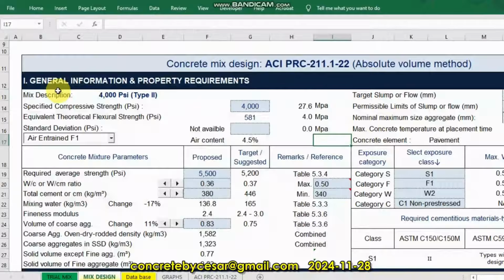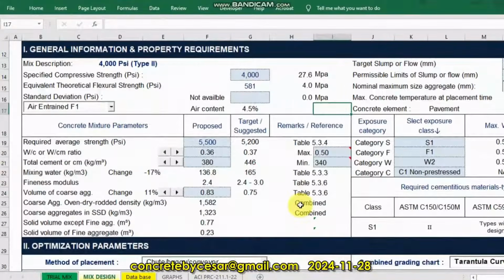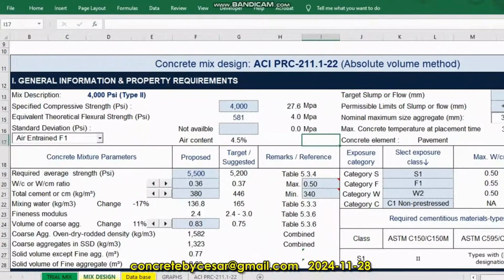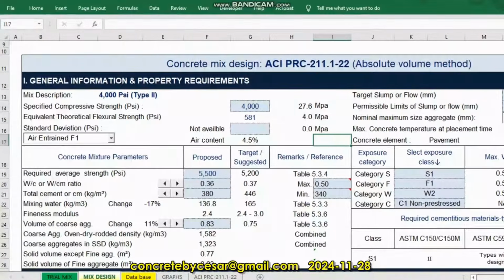So going back to section 1, general information and property requirements. That will be this area. Starting with the specified strength, let's say we are required to produce minimum 4000 psi, which is 27.6 megapascal, with the equivalent theoretical fractional strength of 581 psi or 4 MPa. If you have standard deviation available, you can always write it here. Let's say, for example, 500. So automatically, the required average strength will appear here.